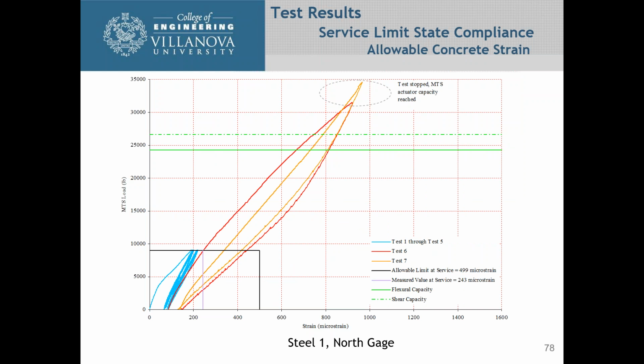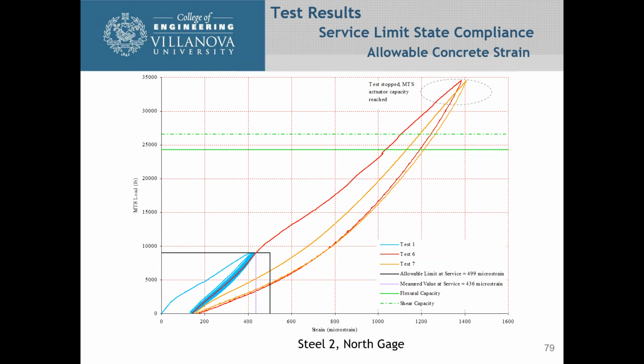Now we're going to look at the concrete strains, and this is for the steel sample. We're going to look at the gauge on the north side of the concrete, and the allowable was 499, and here our measured value was 243, so we're in compliance. For the second beam that we had steel reinforcing in it, we were a little closer. We had 436 microstrains, but we're still within compliance.